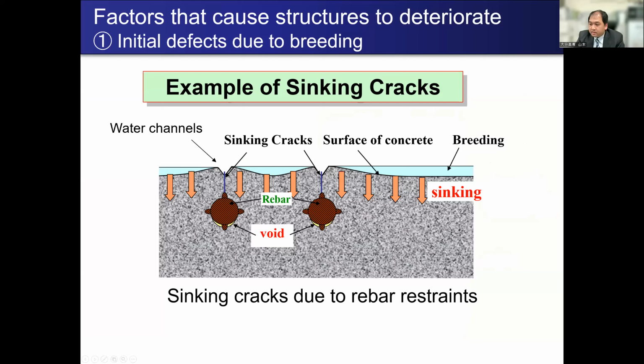Second, this figure shows sinking crack. Sinking crack means that if bleeding occurs in the concrete, the water will rise up. Instead, the surface of the concrete will sink, and the water comes up to the surface. Then the water channel will remain even after the concrete becomes hardened, and the water also gathers at the bottom of the steel. Then after the concrete hardens, this area becomes a kind of void. This is sinking crack.